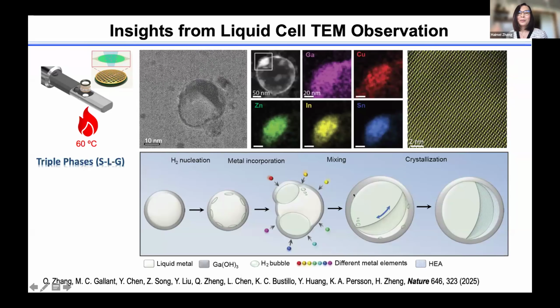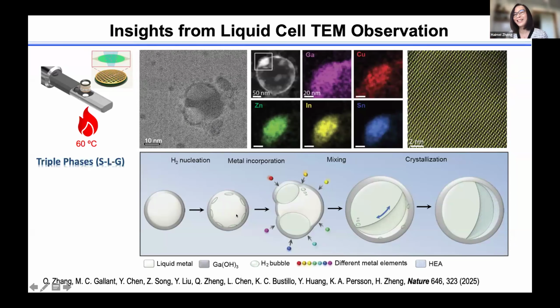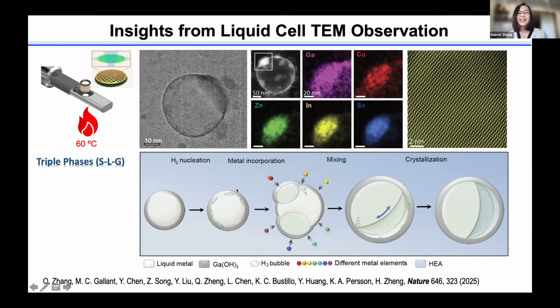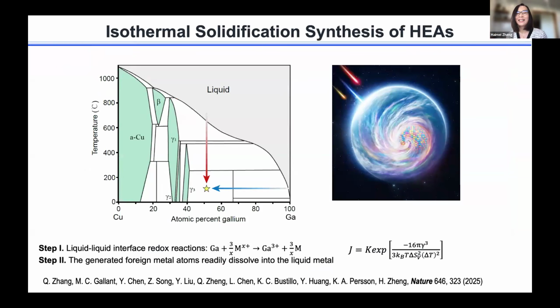This is gallium reduction, and at the interface it generates hydrogen gas. So it is like a natural reactor here, showing this bubble. It comes from the gallium reaction, but there are no beam effects outside of the microscope because we are making large amounts. We apply this high entropy alloy particle for catalysis, for coating, and for many different applications. And this is just inspiration.